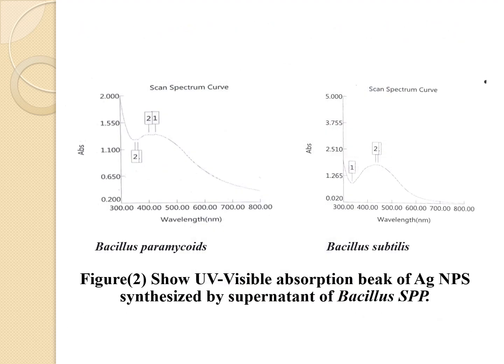The figure shows the measurement of UV-visible spectroscopy, where we can observe an absorption peak located between 404 and 444 nm, which suggests the presence of surface plasmon resonance of silver nanoparticles.